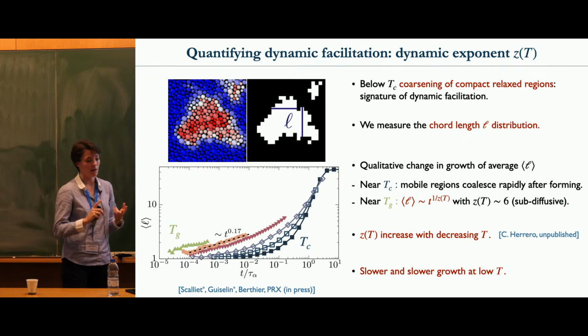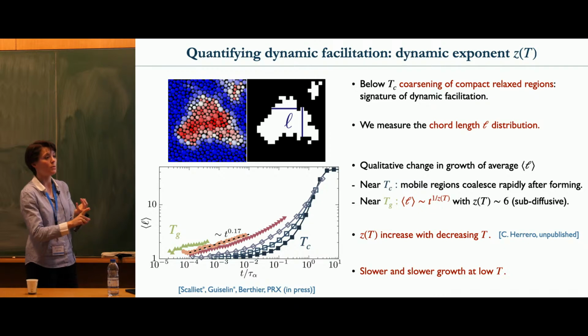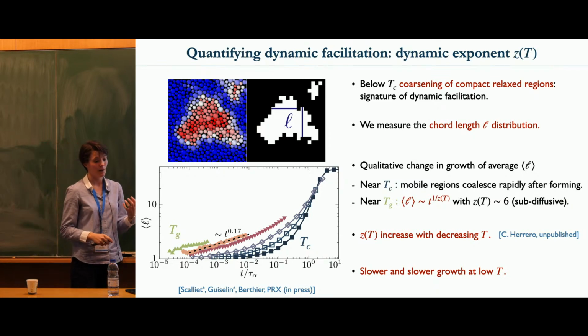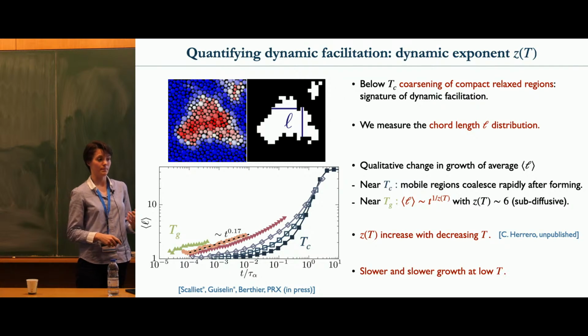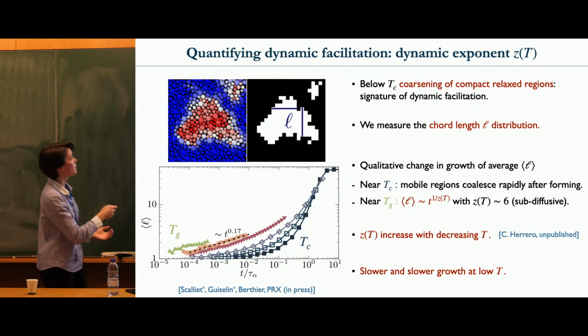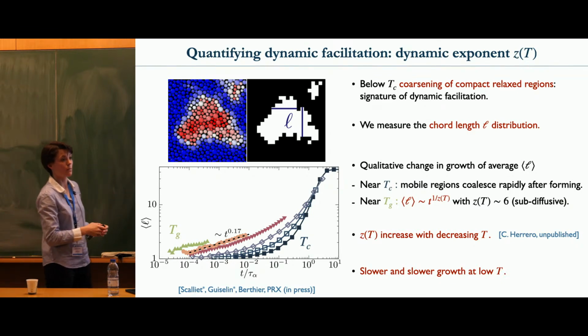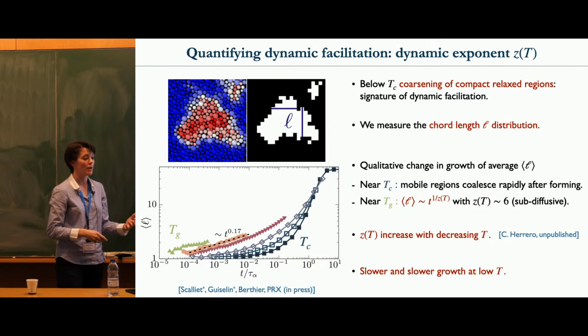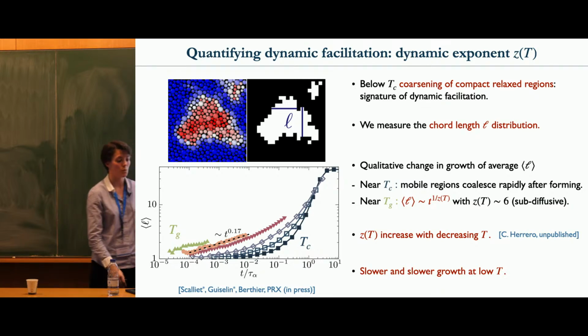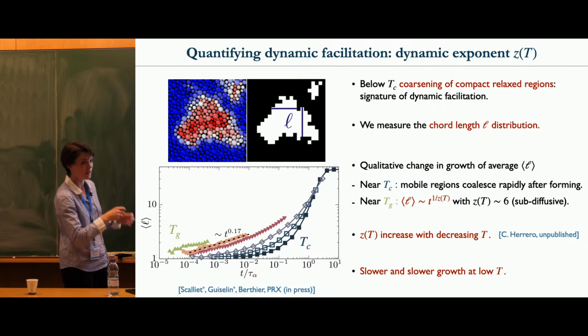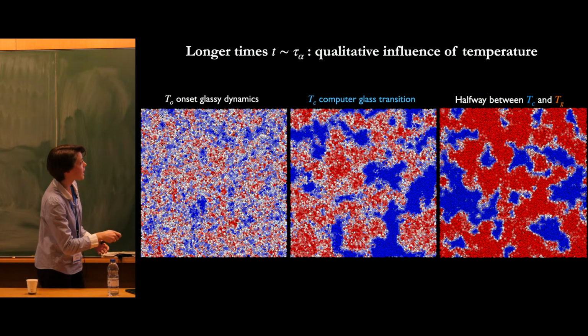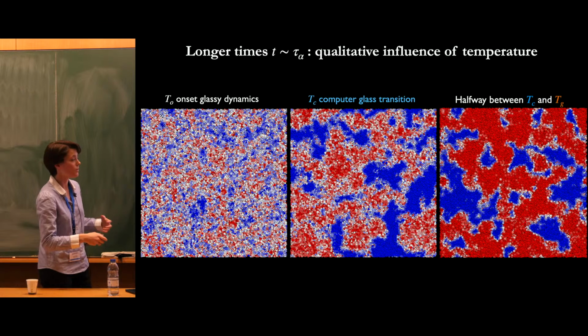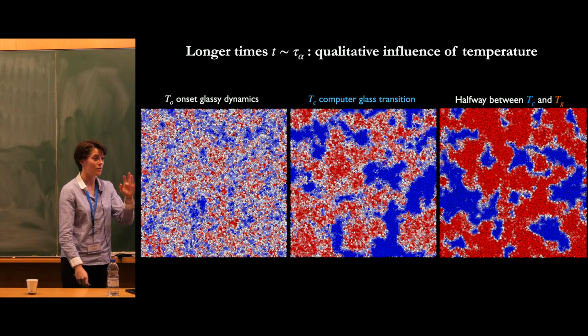The second advantage is that the 4-point measurement actually changes as a function of the ensemble, whether NVT, NPT, or NVE. It suffers from the ensemble: changing the ensemble affects the measurement. Here, this is really a length of something you can see, so it shouldn't suffer from this. I think the reason people used this 4-point correlation function is precisely because at the temperatures where simulations were done, you didn't have this clear distinction where you can say, this is my relaxed cluster, it has well-defined boundaries, and I can give it a size. Here, maybe you can, but the boundaries are not so sharp, so you need to do this 4-point correlation. Here, it's even worse. I don't even know how to define a cluster. But it's the same information.